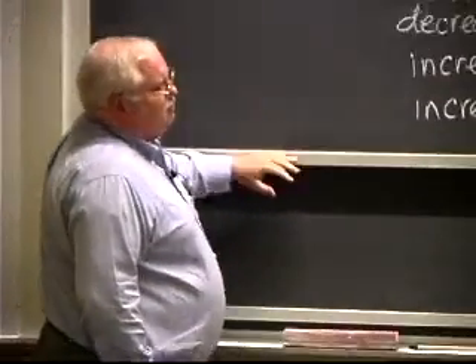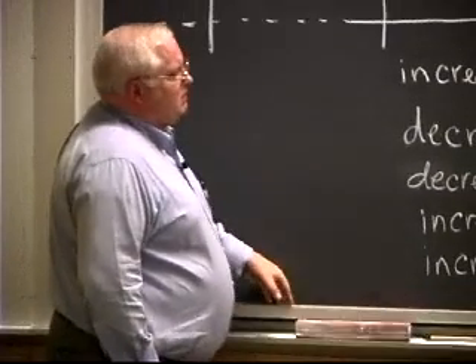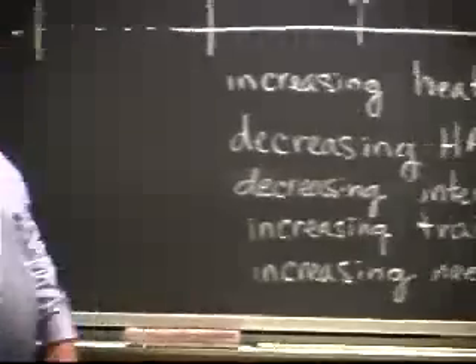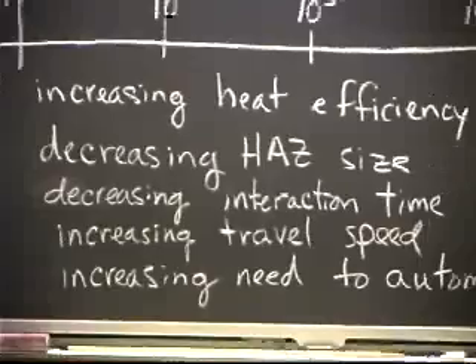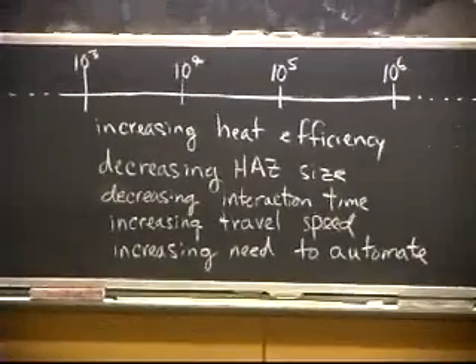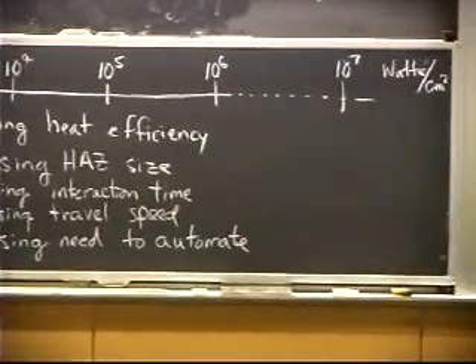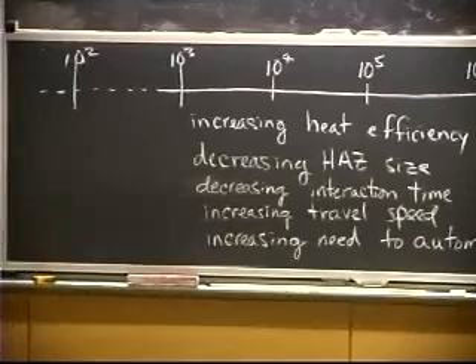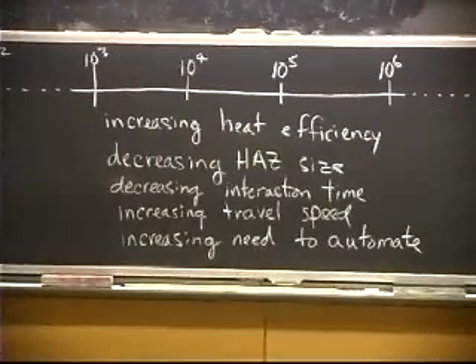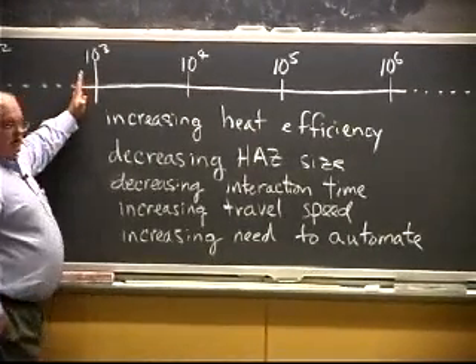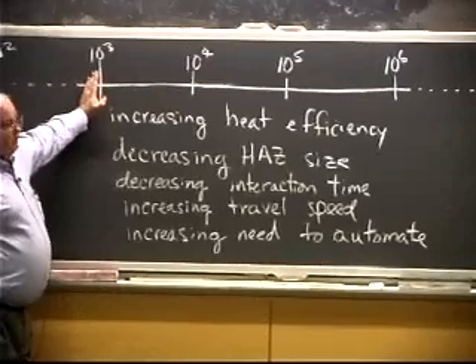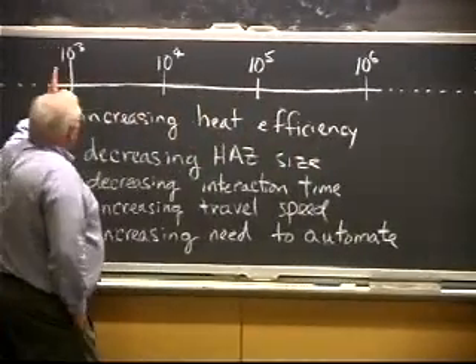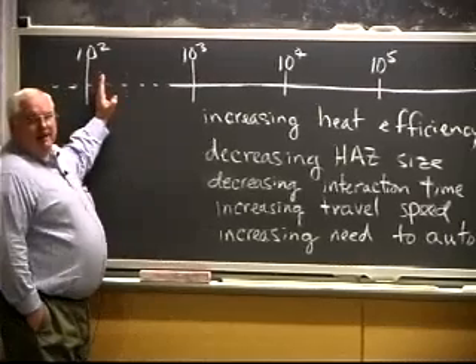Now, if I want to start looking at fusion welding, you can go back to some very basic physics and say, for a typical metal, how much heat intensity does it take to cause melting? And it turns out that for a typical metal, you cannot get melting with a heat intensity on the surface. This is heat intensity in watts per square centimeter. You cannot get melting if you have less than 100 watts per square centimeter.